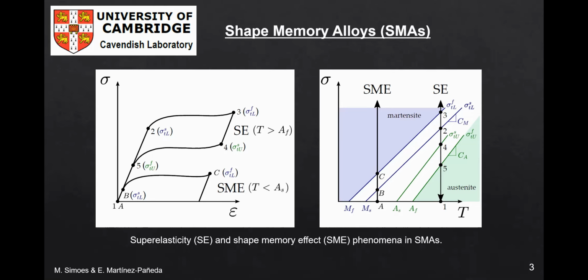As shown in the left figure, two phenomena are intrinsic to shape memory alloys and their phase transformation: superelasticity, SE, and shape memory effect, SME. Only superelastic alloys such as nickel titanium can achieve full strain recovery when the load is removed, showing a hysteresis loop in the stress versus strain response. And shape memory alloys experience the shape memory effect, show a large residual strain after unloading, and require a change of temperature to recover their original shape.